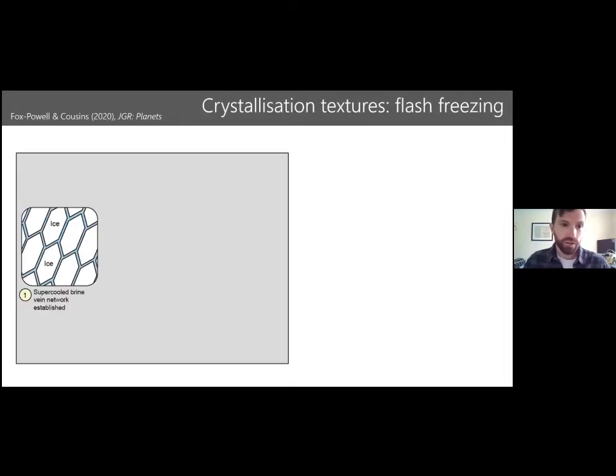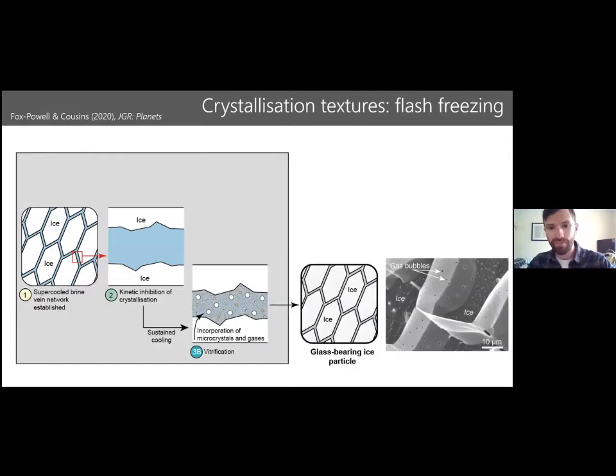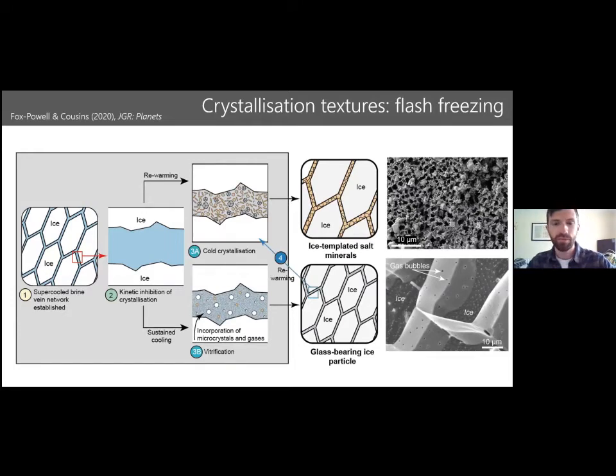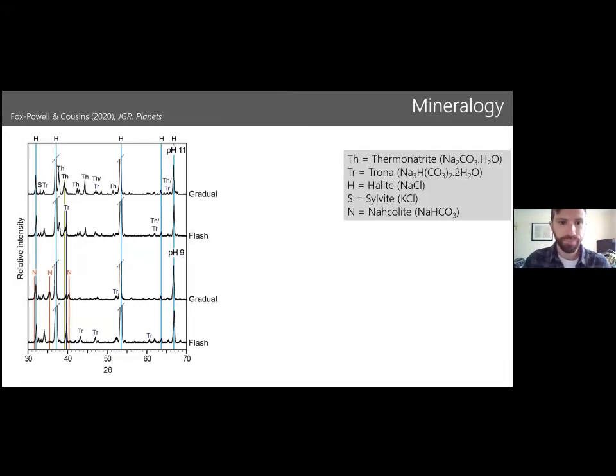By contrast, in the flash frozen samples, again, we have a brine vein network established. We saw that in the SEM images. We have the inhibition of crystallization. And then what happens subsequently is really down to the subsequent thermal environment that these samples experience. If rapid cooling is sustained, then we can get vitrification and glass formation. But if rewarming happens, then we can form these crystalline salts, which are all forming more simultaneously and without the spatial reorganization we saw before. So they end up with this homogeneous texture.